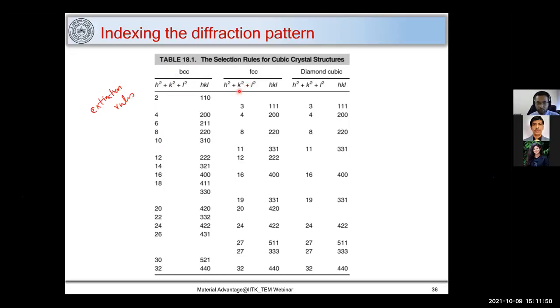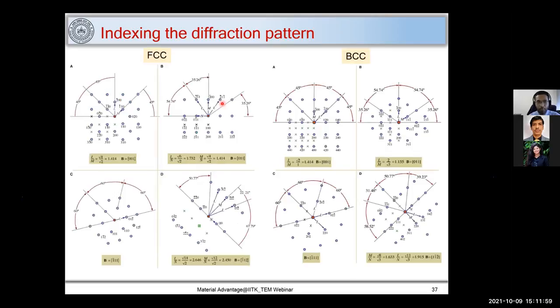There are different extinction rules, and this table is readily available. So you should know which planes are going to diffract and give you a diffraction pattern in TEM. Now, these are the standard diffraction patterns available for both BCC and FCC at different zone axes. What do I mean by zone axis? If I consider this as a zone axis, all these planes will be parallel to this zone. That is what zone axis means. When you index any plane or any pattern, you always mention the zone axis. These standard patterns are always available in the textbook.